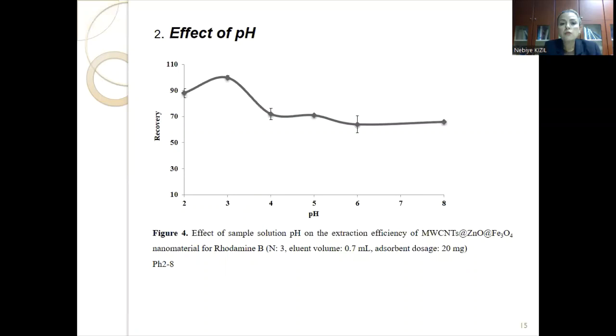Now we optimize our method. For this, we have tried to find the optimal pH because pH is one of the most important parameters. For this, sample solution pH was adjusted from 2 to 8. Optimum working pH was chosen as 3. That's why follow-up experiments were carried out at pH 3.